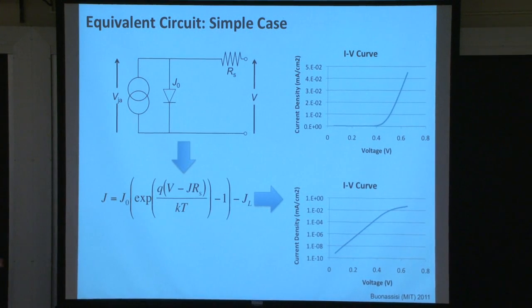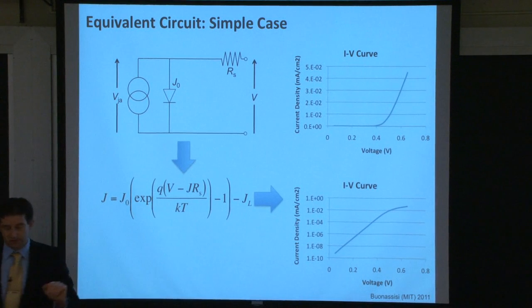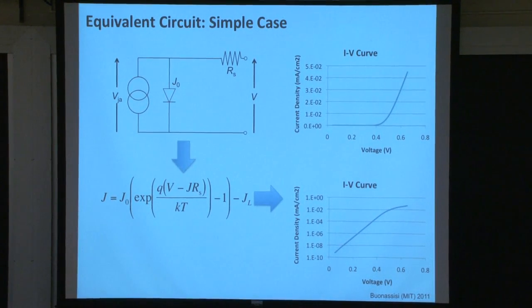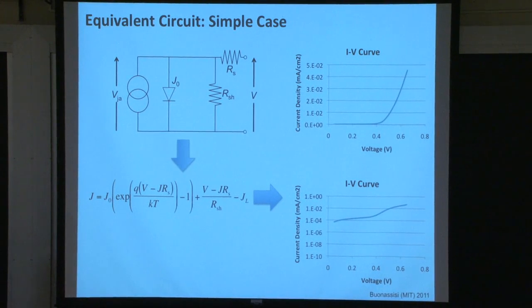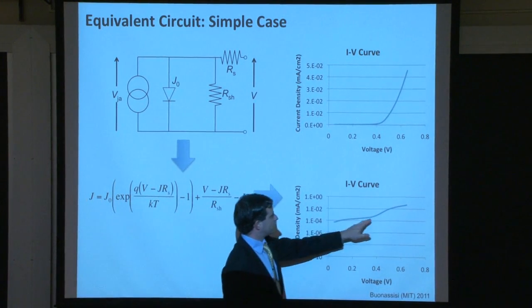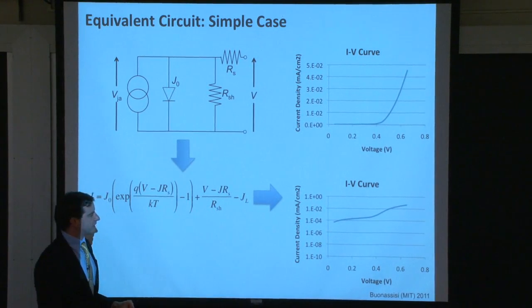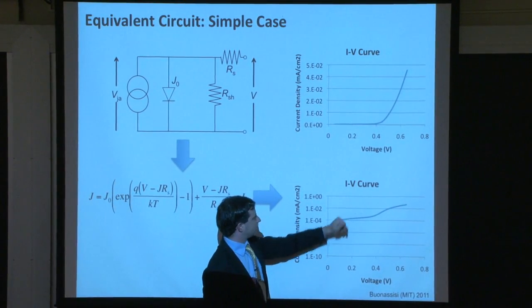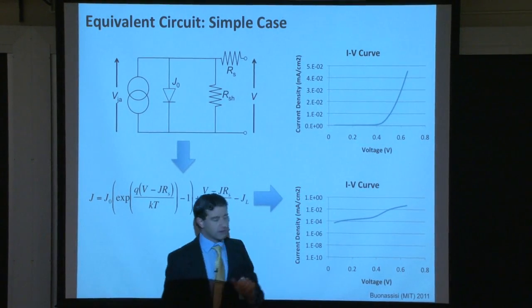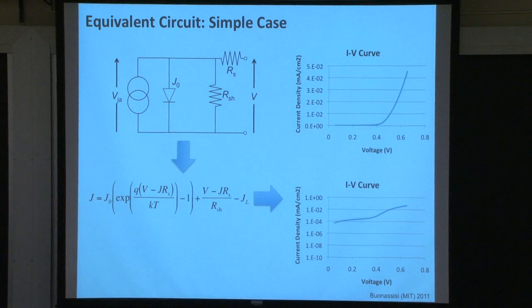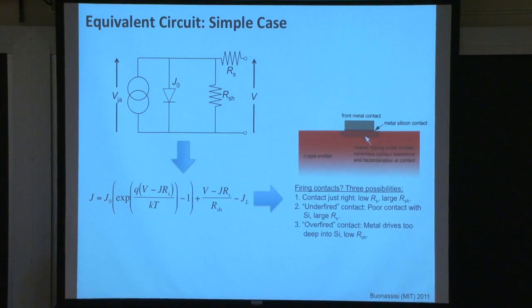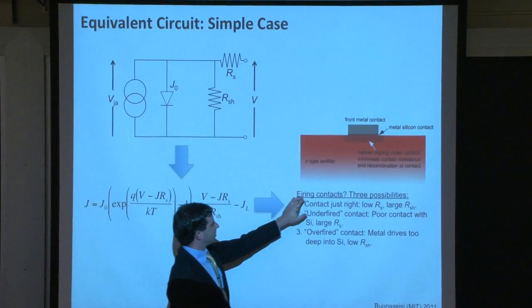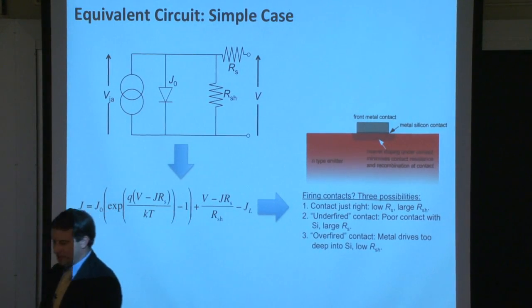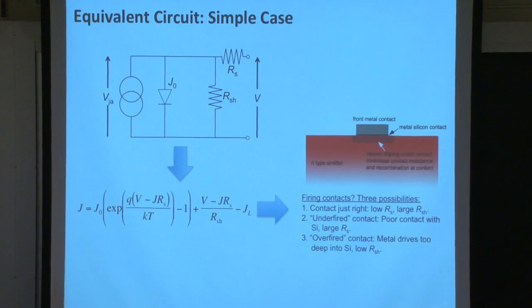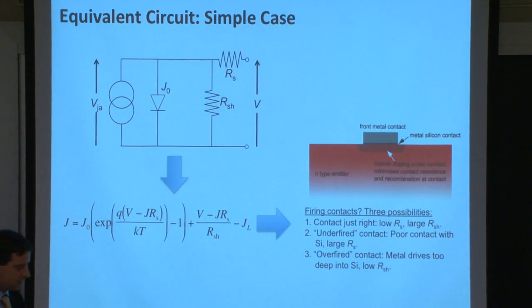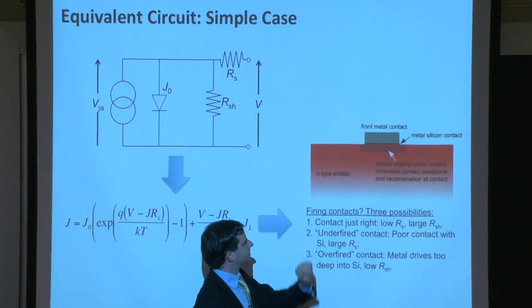So contacts, when improperly performed, can add a series resistance component, a rather significant one, and drop the performance of your device. Likewise, shunt resistance, we saw a simple effect right here of shunt resistance. If the shunt resistance goes down further and the saturation current goes up even higher, it begins to affect the fill factor as well. And so shunting can also be impacted by contacts, particularly when you fire your contacts. In other words, when you heat your stack up to create good contact between the metal and the semiconductor underneath, or the TCO and the semiconductor underneath, a couple of things can happen.